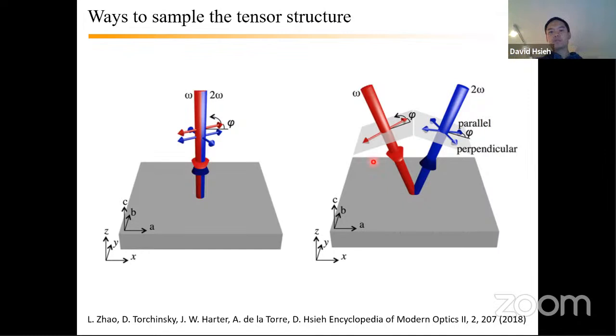You could get around that by coming in at oblique incidence, thereby creating a Z component of your field. And one simple way to do that is just to adopt this oblique incidence geometry setup, where you're now rotating the electric fields of the incident and outgoing beams as a means of sampling different tensor elements.